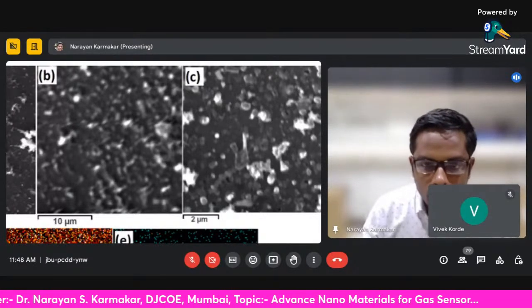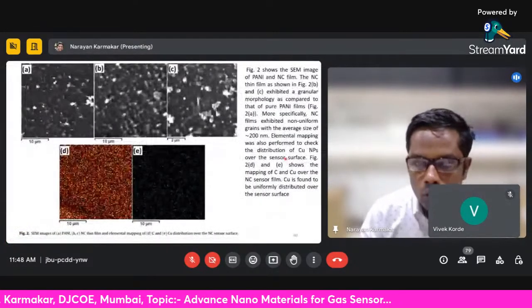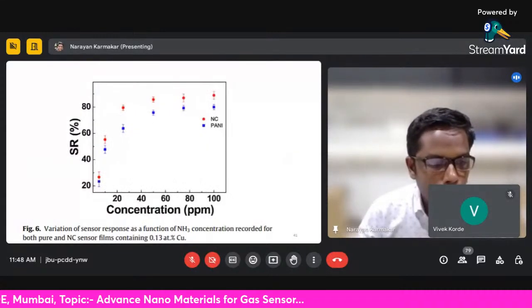We optimized this and found that a concentration of about 0.13 atomic percent of copper is best suitable for the sensor.